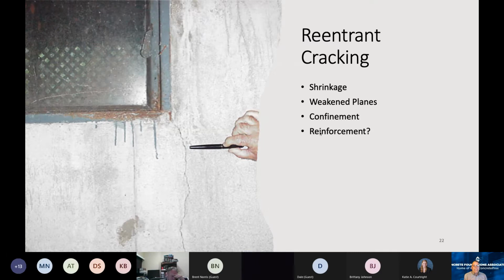But a reentrant corner is basically any time you see an interior corner to a concrete mass, or where the concrete kind of turns at 90-degree angles on itself. And that means that there's going to be shrinkage stress. If you can imagine those two sides, so we'll call this side 1 down below the window and this side 2 up high on the window. Down below the window, it's part of the wall that goes to the left off that window. And so there's shrinkage forces that are trying to pull that concrete to the left. At the same time, all the way up above the window and to the right, that higher wall section is shrinking at a different rate off to the right. And where's the weakened plane? It's right there at that corner.